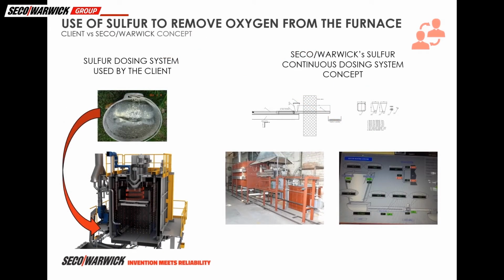First idea was to use sulfur for this purpose, because such solution was used by the customer at that time. It was one of the recommended also by international standards. The customer dosed the sulfur in the furnace in a very simple way. A bucket filled up with sulfur was placed in a heating chamber. Under the influence of temperature, sulfur combustion and consumption of oxygen took place. One of the drawbacks of such system was the lack of control over the amount of sulfur. Therefore, at the preliminary stage of the project, we designed and wanted to use a continuous sulfur dosing system. We made our own tests with sulfur using our lab furnace. On the slide you can see the system used by the client on the left and our design on the right.